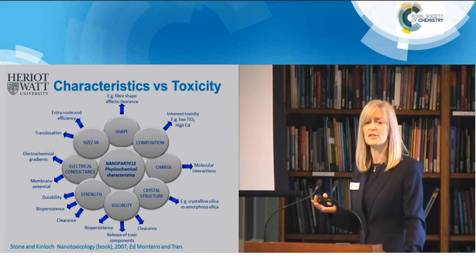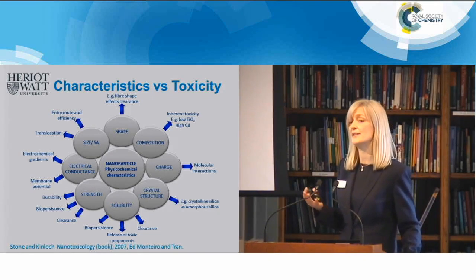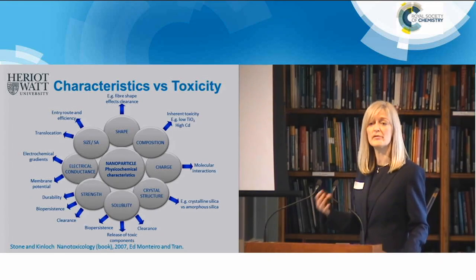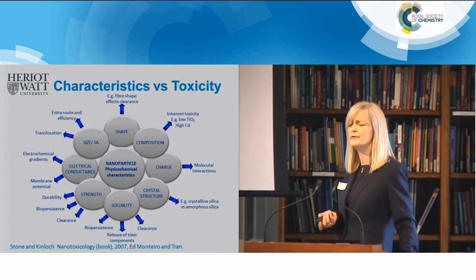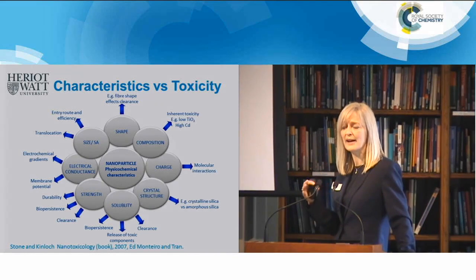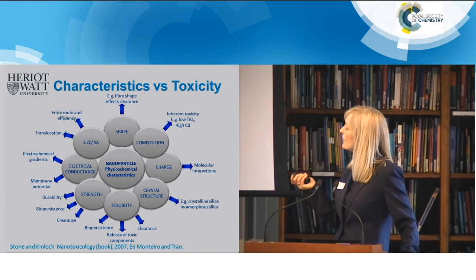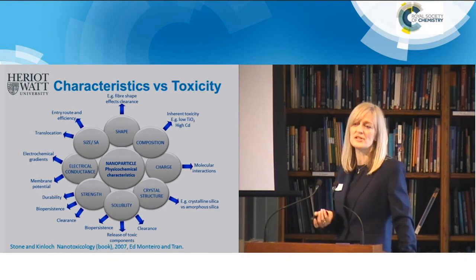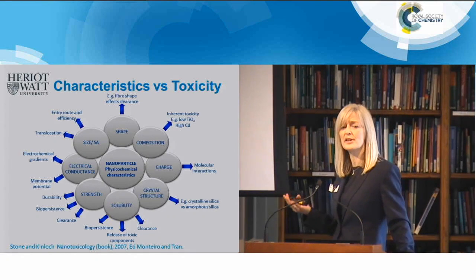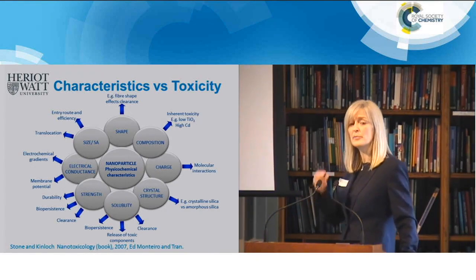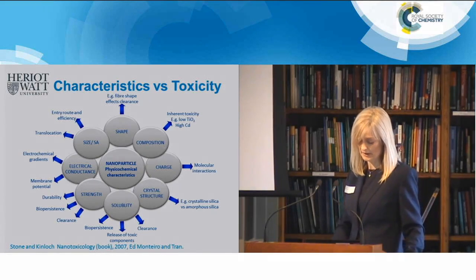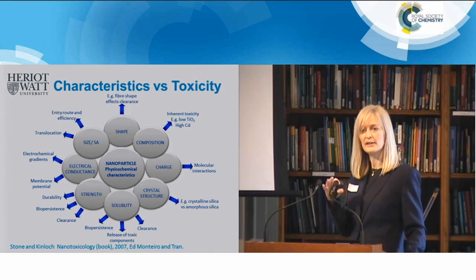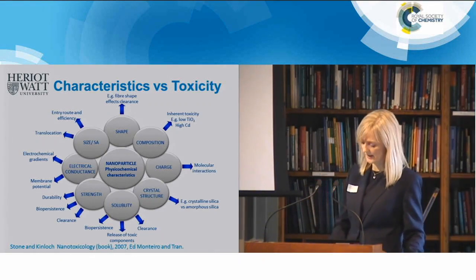Solubility is important. If a particle is soluble, it's not going to be biopersistent. But if it contains toxic metals or toxic materials that can be released due to that solubility, then that can contribute to their toxicity. Strength is important, especially for fibers. Fibers which are brittle can break down, and this can influence their ability to be cleared from the body. This slide was put together in 2007, and then I used the term electrical conductance. We thought that electrical conductance might be important in determining toxicity, and in fact, a group in California with Andre Nel have shown that the ability of electrons to move within metal and metal oxide crystal structures, known as a band gap, is important in determining their toxicity. So there's a whole host of physical and chemical characteristics that need to be considered, not just size.